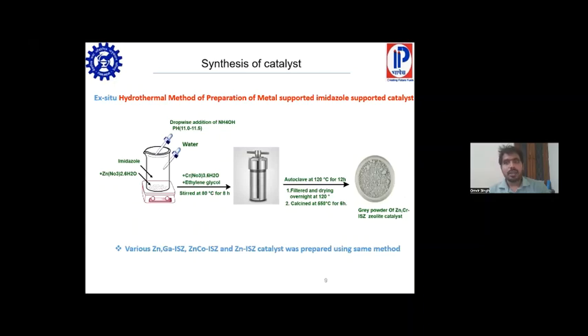Then comes the second hydrothermal method, in which first imidazole and different metal salts were homogenized in water. After that, ammonium hydroxide was added, then ethylene glycol, and the solution was stirred at 80 degrees for 8 hours. After that, autoclave the solution at 120 degrees Celsius for 12 hours and filter. Then dry overnight at 120 degrees Celsius. Then calcine at 550 for 6 hours. We obtained the zinc chromium imidazole catalyst. In the same way, other catalysts were also synthesized.